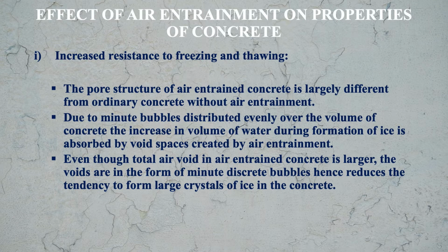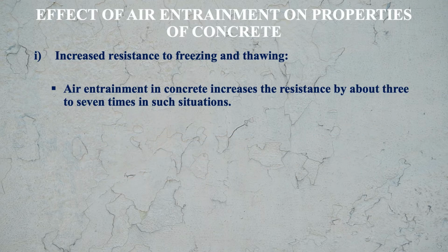Even though total air voids in air entrained concrete is large, the voids are in the form of minute discrete bubbles. They are not interconnected. Hence it reduces the tendency to form large crystals of ice in the concrete. So this way it helps. Air entrainment in concrete increases the resistance by about 3 to 7 times in such situations. So this is the advantage of using air entrainment in concrete.